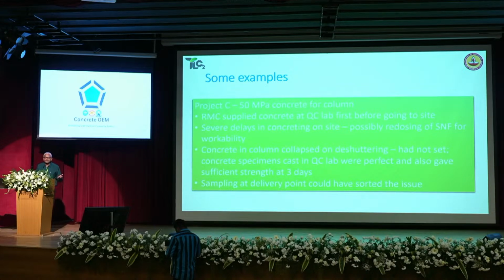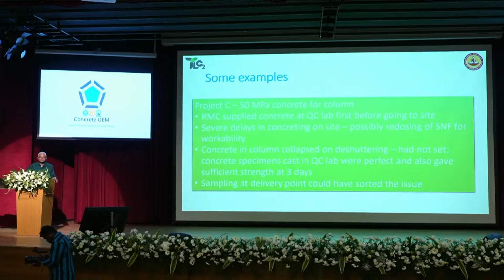Now, when concrete gets delayed on site, what happens? Slump gets reduced. When slump gets reduced, the old technique was to put water to increase the slump. Luckily, people have understood that this is a problem. More water means less strength, less durability. Now we start adding admixtures. We start adding chemical admixtures to ensure that we can retain the slump.